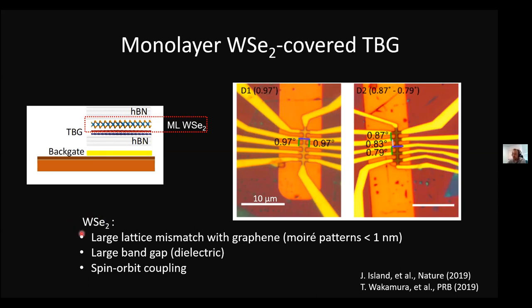One important point in using tungsten selenide is that it has a large lattice mismatch with graphene, so there's no Moire physics between the tungsten selenide and graphene. Effectively, it's a large band gap material, so you can think of it as a dielectric, and it provides some spin orbit coupling that I'll discuss more towards the end of the talk.